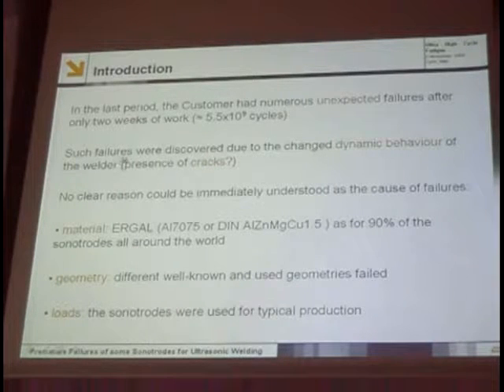Such failures were discovered due to a change in the dynamic behavior of the welding equipment. Usually we know that when the dynamic behavior changes, when the compliance changes, it is because cracks have been introduced in the system. So perhaps it was a problem of the presence of unexpected cracks in the sonotrodes. But at the beginning there was no clear reason why these sonotrodes failed, because the material is Ergal, which is a commercial name for the 7075 aluminum alloy, and Ergal is used for 90% of the sonotrodes all around the world. So the behavior of this aluminum alloy in producing this type of tool is very well known.